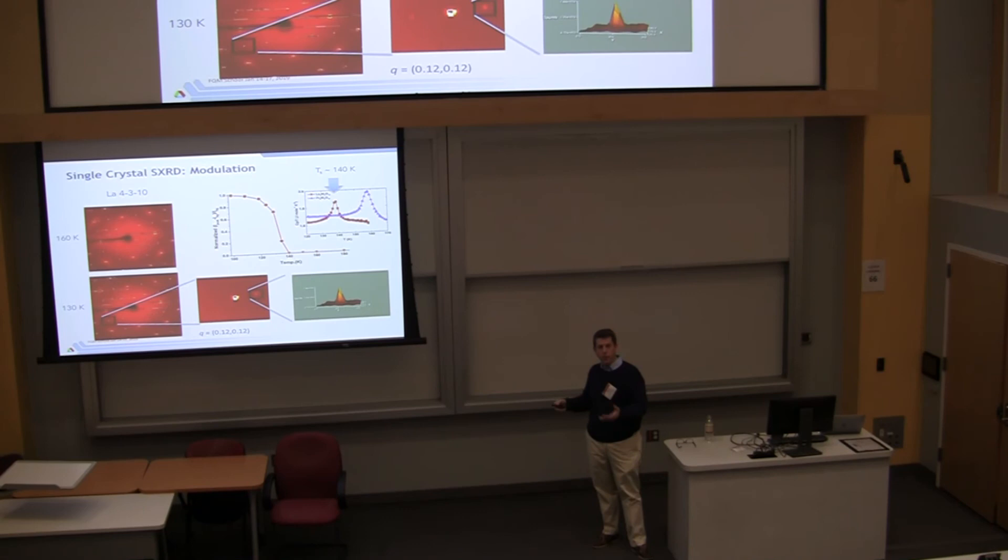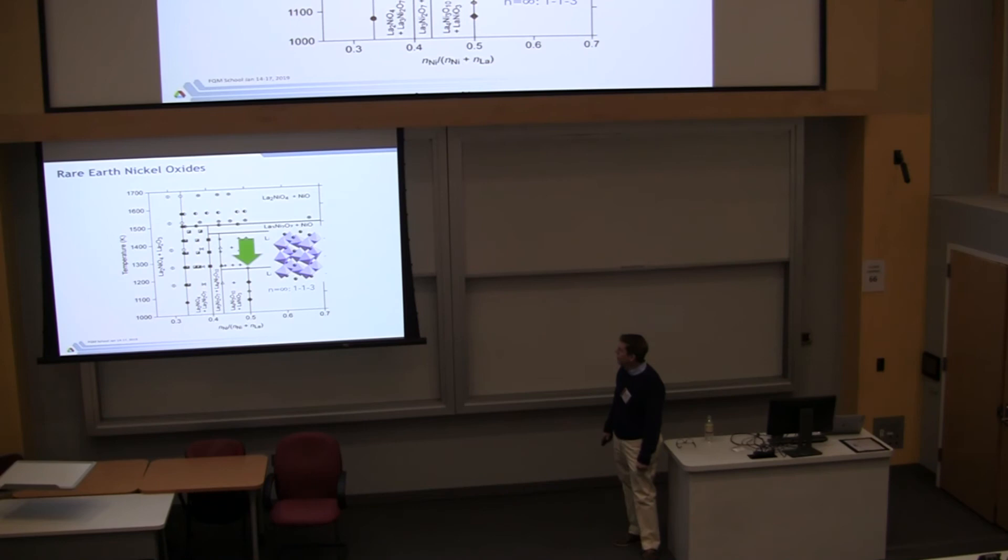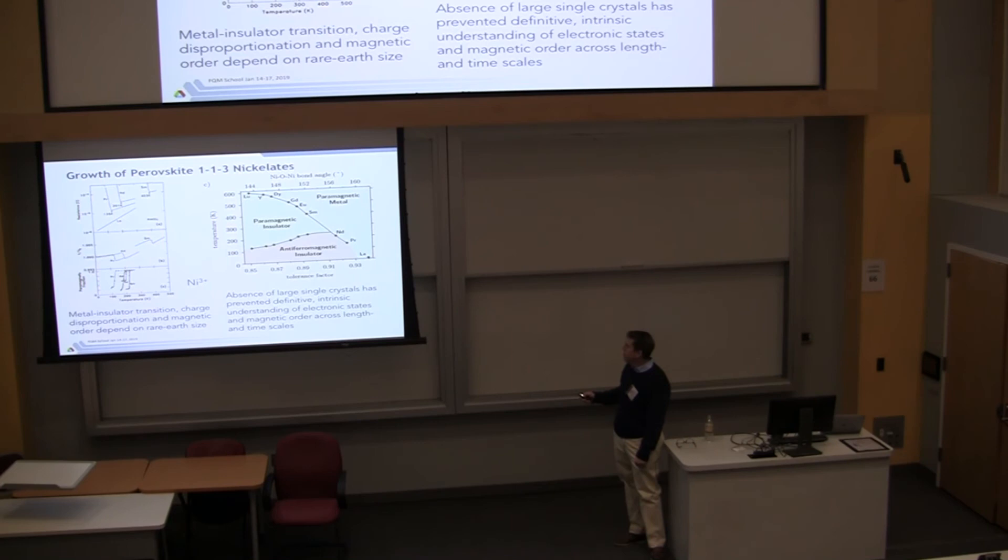But then we said, look, as we go this direction, we're putting more nickel 4 in here. So we're trying to oxidize this nickel from 3 to 4. Maybe using high pressure, we can stabilize deeper into this phase diagram. And so we did, and we grew these crystals. They're not so great looking, but we were able to cleave out pieces. And here's a diffraction pattern. So we made the phase. And then we were able to study it. And what we found here is that above room temperature, there's a feature.